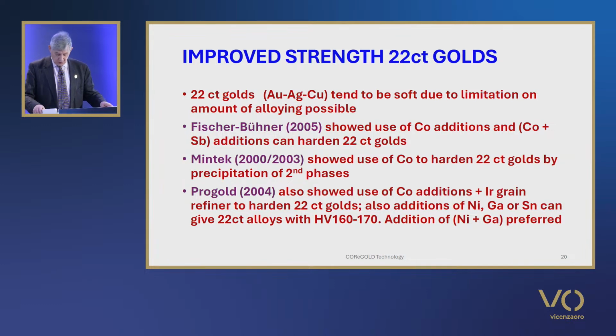Work at ProGold on hardenable 22-karat gold is described in a 2004 paper which initially examined the effect of cobalt and iridium grain refiner additions on 22-karat gold, silver, copper, zinc alloys. And it was made using a 95% copper, 5% cobalt master alloy. The highest hardness of 230 Vickers was obtained by aging a gold, 3.7% silver, 2% copper, 0.6% zinc, and 2% cobalt alloy, yet again demonstrating the effectiveness of cobalt additions. The effect of other alloying additions added via master alloys, such as nickel, gallium, and tin, gave gold alloys of good colour that could be easily attain hardness values of 160 to 170 Vickers, with an addition of nickel plus gallium being preferred.